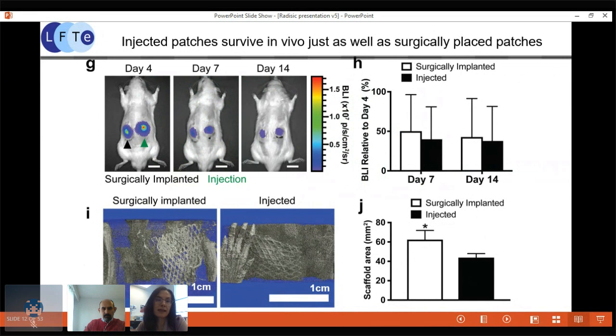So what Miles did is he transfected cardiomyocytes with luciferase, and he used a syngeneic recipient to isolate cardiomyocytes. So this is all done in Lewis rats with Lewis cardiomyocytes derived from neonatal pups. And so if you look at injected tissue on the right and surgical implantation on the left, you can see that there is no difference in the bioluminescence signal over a period of 14 days, which tells us that there wasn't appreciable damage to the cells done initially that could affect their function later on.